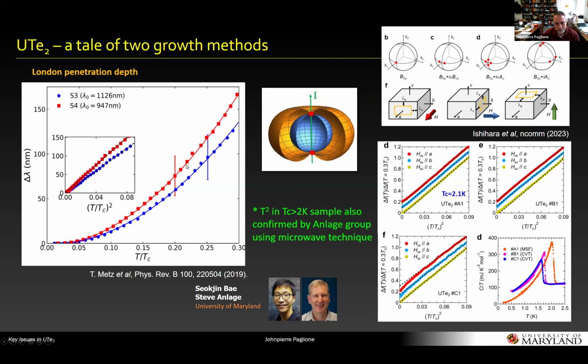These were on the first generation samples with 1.6 Kelvin TC. Since then, there's been further work by the Ishihara group on higher TC samples, and they see basically the same thing. There's some slight difference in power laws, but they're all pretty close to T squared. And the interesting thing here is that